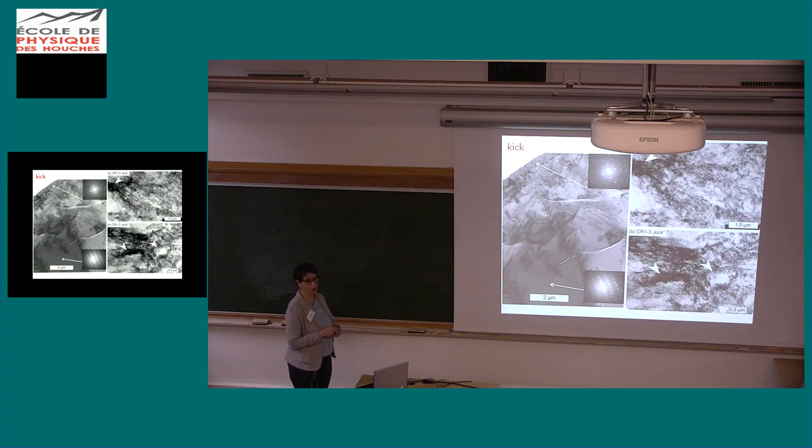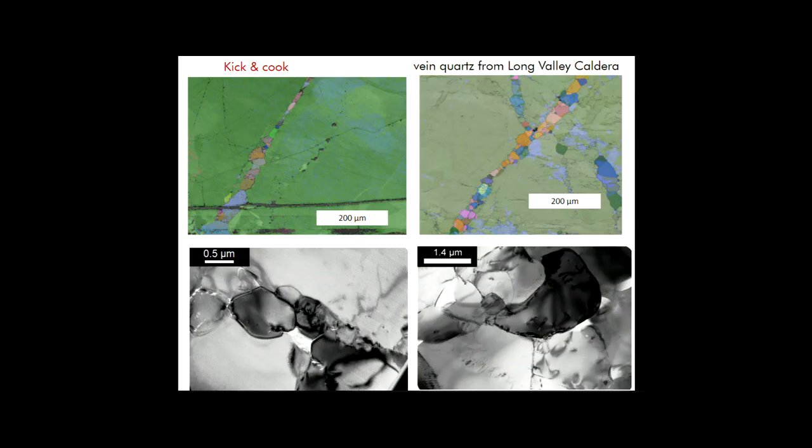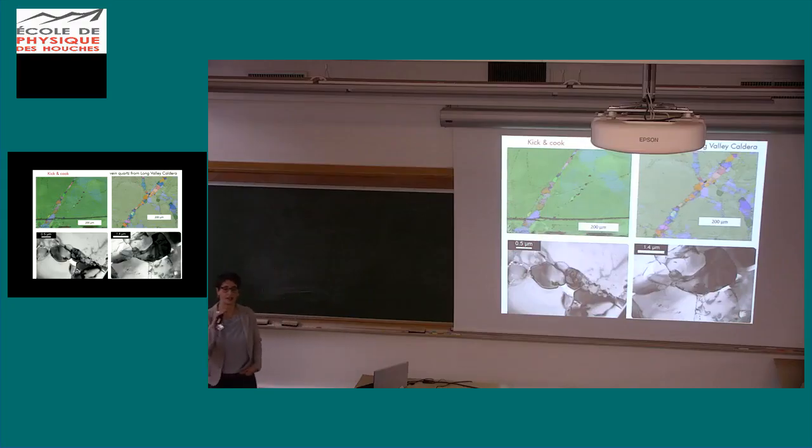And then we have also these microlites. And these are, of course, very important sites for the annealing afterwards. So what is happening with exactly these sites during annealing, during the creep stage? We do see growth of new crystals, and these have a completely different crystallographic orientation than the host.